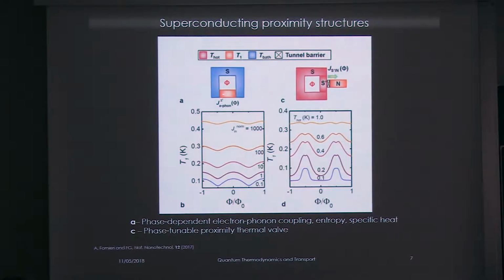So, for instance, in this case, the electron-phonon coupling of the orange part of the proximized metal becomes phase dependent. So this is a nice way to control the rate at which our, let's say, engineered superconductor can exchange heat between electrons and its phonons, okay, thanks to the phase. So this is a sort of knob that allows us to control the amount of exchange.